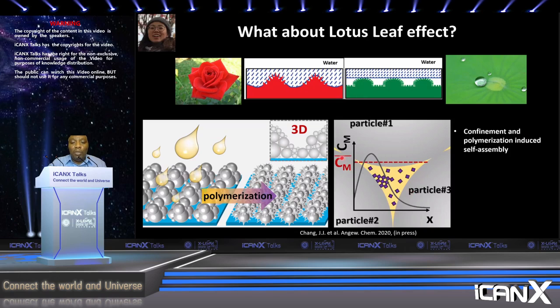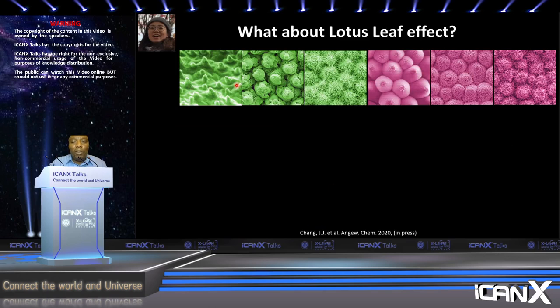And one of the things we used is capillary confinement, because we know that if you have etch component and you have evaporation, and as you form these capillary bridges in tightly packed particles, then you will end up creating a huge concentration of the etched metal ions here, which can polymerize and grow, creating new features on those particles. And when we did that, we can actually create all sorts of features. Here is one of them that is created in the confinement, where the particles are still within the metal mold, within the PDMS mold. And here is another one that after we make a rose flower, we etch it and we grow these hairy kind of structures on top of that. And we can do this whether we have a two-dimensional film or a three-dimensional textured structure of these metal particles.